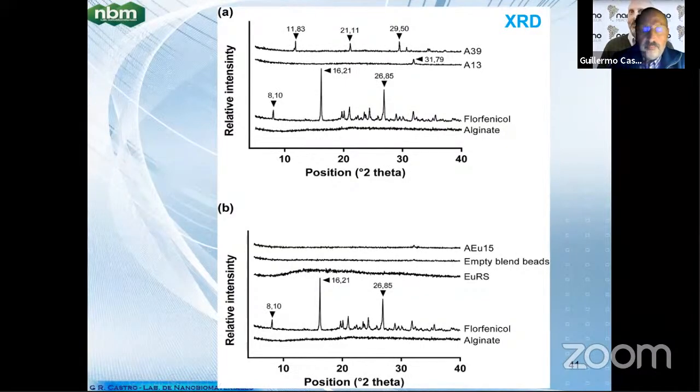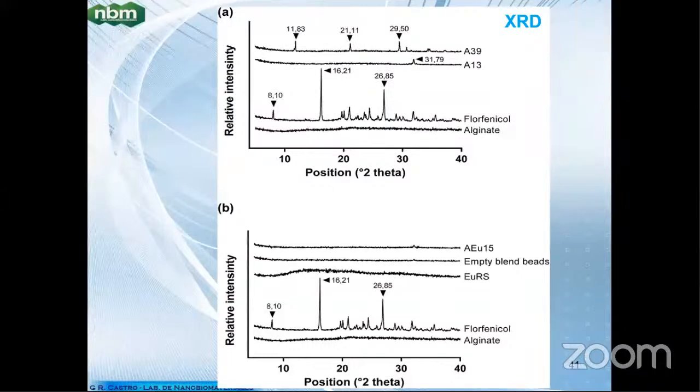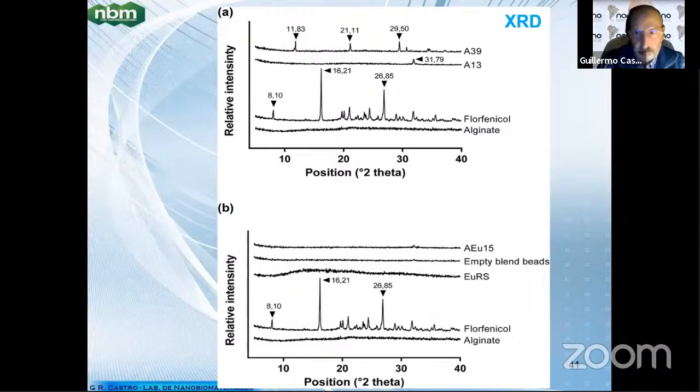As I mentioned before, when a drug crystallizes inside the structure, it is very difficult to dissolve, and in such a case the energy required is very high. In some cases this is not possible and can create serious physiological problems for the person. So look at what happened with the blend. There are no crystalline structures at all. And this is very, very important. It means the drug is inside the particles in an amorphous structure.